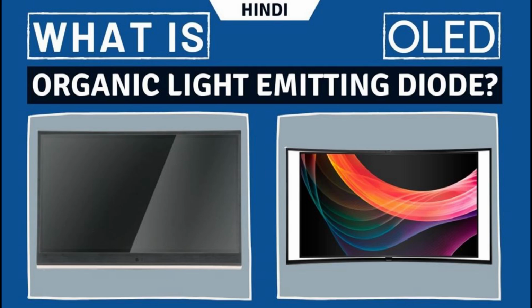In 2012, OLED lifetime to half of the initial brightness was improved to 900,000 hours for red, 1,450,000 hours for yellow and 400,000 hours for green at an initial luminance of 1000 CD/M2.